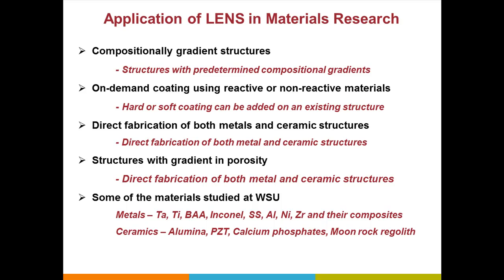Tantalum, it melts at over 3000 degrees Celsius. Titanium, obviously many groups do it, we have done it. Bulk amorphous alloys, I'll show in a couple of slides. Inconel, stainless steels, we have also done aluminum - it's not easy. In a 500 watt system, we have done aluminum with some silicon in it. Also nickel, zirconium, and composites of many of these systems. On the ceramic side, we have done pure aluminum oxide, lead zirconate titanate or PZT, calcium phosphate, and moon rock regolith or moon rock simulant ceramics.